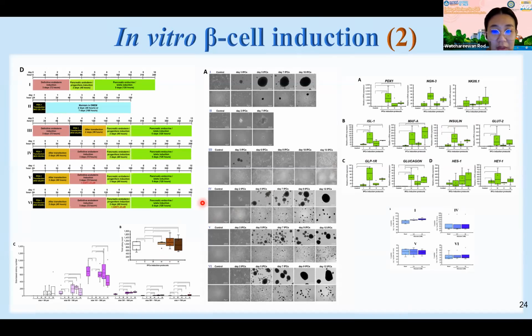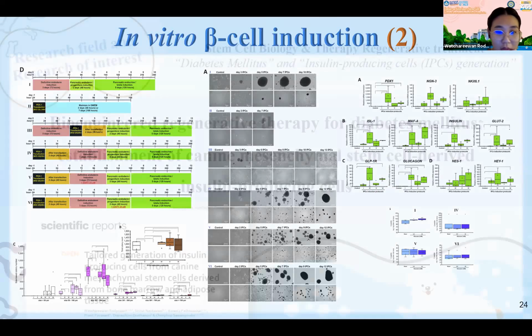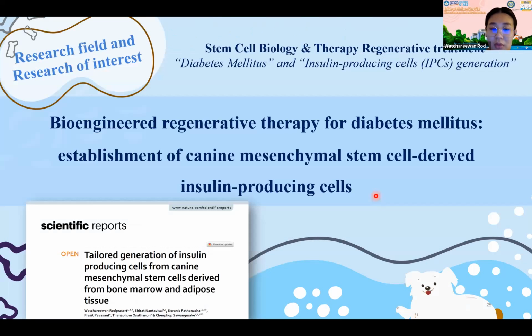However, in this study, we also established the protocol with DAPT to get more cells. But we found that the number did not increase that much. And the gene expression was not comparable to when we did not use DAPT, the Notch signaling inhibitor. So from this result, it led to our study about canine mesenchymal stem cell derived insulin producing cells.